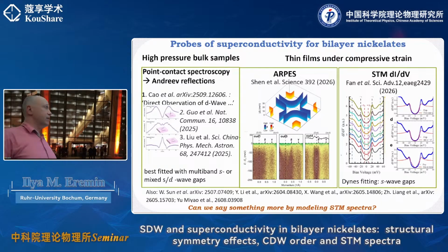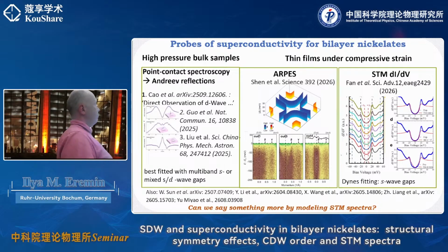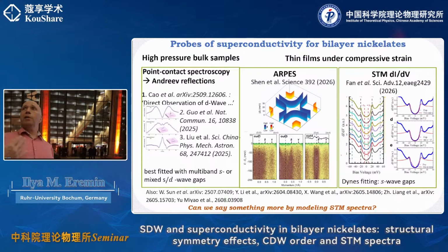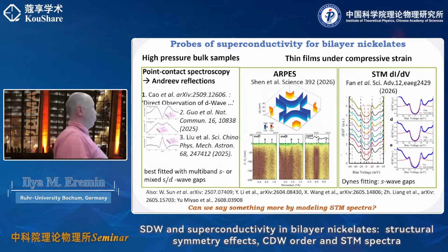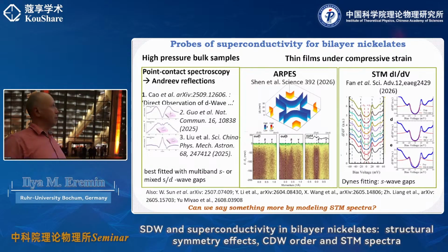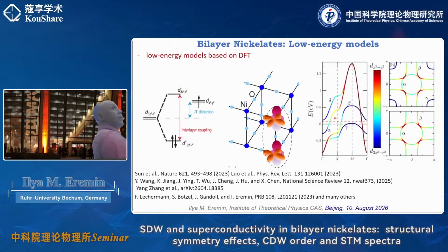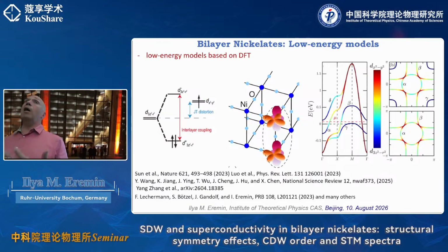But if you look at the STM data, and the behavior of the dI/dV curves that you see in STM, if you do, let's say, a simple-minded Dynes fitting of this, you also come to the conclusion, and this is also the conclusion of Haihu's group, the first group that did these measurements, and we were also part of it, that it comes out to be an S wave. However, this assumes that you have a simple Dynes-like fitting. We know that if you deal with STM, it's important how the current is tunneling into the sample, and this is especially true in a multi-orbital system. And we know that the nickelates are multi-orbital systems.